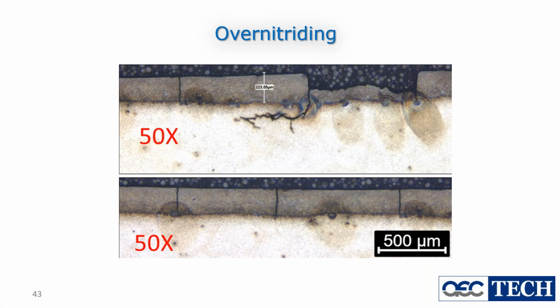Yeah, this is another example of overnitriding. This is not a re-nitrided surface. This is a nitrided surface of a die cast tool, which is subjected to thermal shock. This is about 8 to 10 thou of nitride layer. When you get to 10 thou of nitride layer thickness, the nitride is too thick, and during the thermal shock, it will crack. Because the nitride layer has different thermal expansion, it expands differently than the steel. It can crack because it's more brittle.